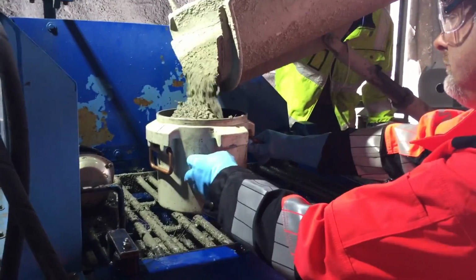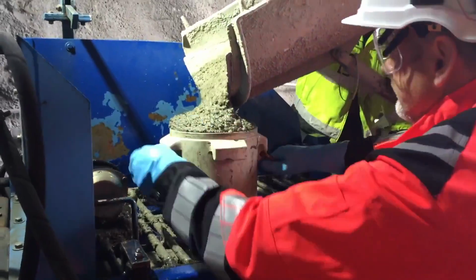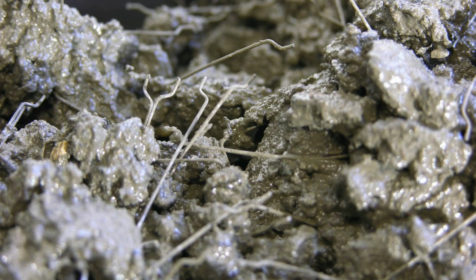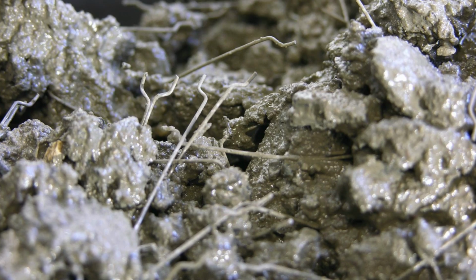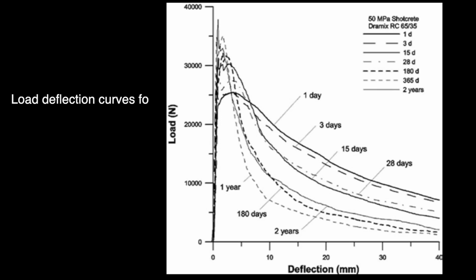At that time, we had not only the introduction of fibers, but we had the general concept that we have to improve the quality of the shotcrete, which depends on the mix design, on the machinery, and also on the skill of the operators. But to keep the balance, you need also to improve the reinforcement, because you need a balance between both materials, which are making just one composite. Well, when they are asking for such a high strength after such a short time, that means that they need it maybe to stabilize the rock. The bond between the rock and the shotcrete is much more important, in my opinion, than just the strength.